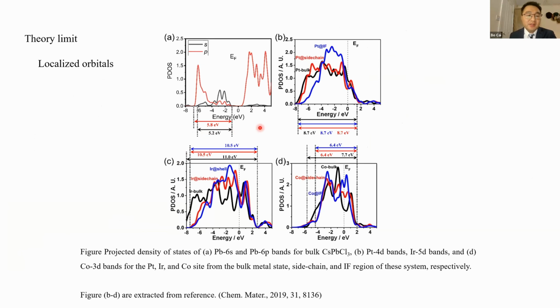This equation is similar to the d-band center theory in the catalysis field. The prerequisite of d-band center theory is a high localization of the d-band. Then we check the bandwidth of the electronic DOS of halide perovskites. Luckily, the bandwidths are narrower than those of the d-band of transition metals in catalysis systems. Then we think that the theory might be suitable for halide perovskites.